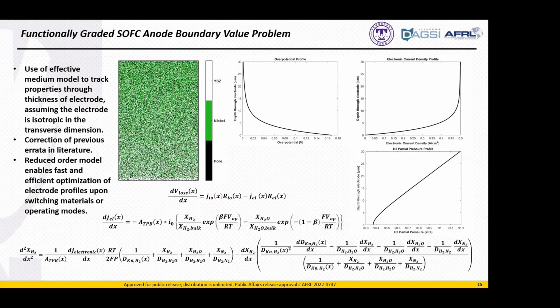Okay. So within, I guess it's opaque here on this slide, this exchange current density term here is also partial pressure or mole fraction dependent, if that's what you're referring to? Well, what I'm referring to is that while the form of the equation is very accurate, the underlying physics that the Butler-Volmer theory was based on was electron transfer at the triple phase interface only. That's the kinetic rate limiting step for that reaction.